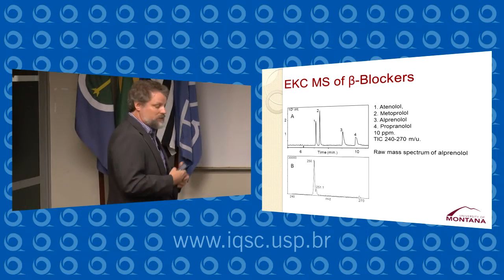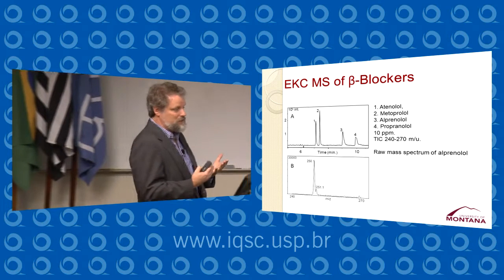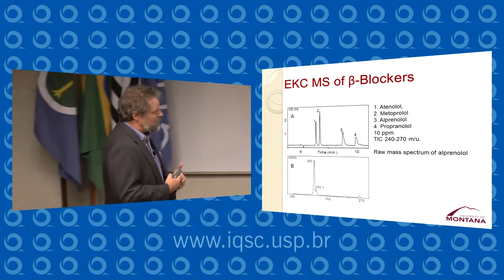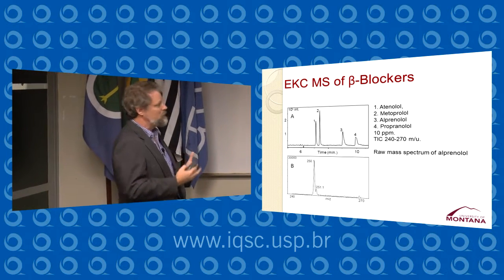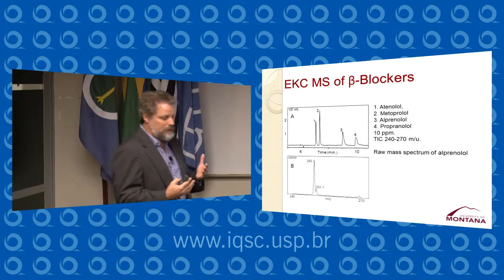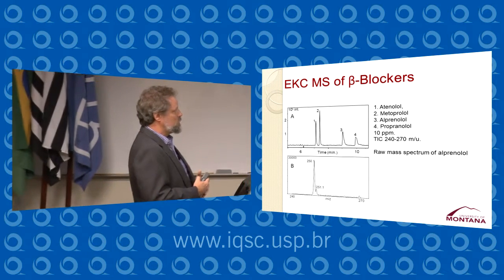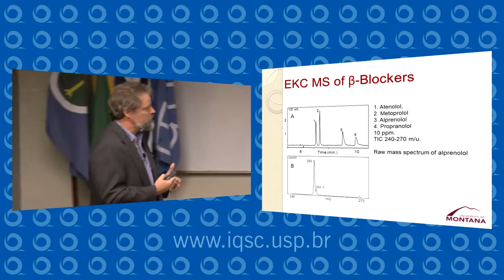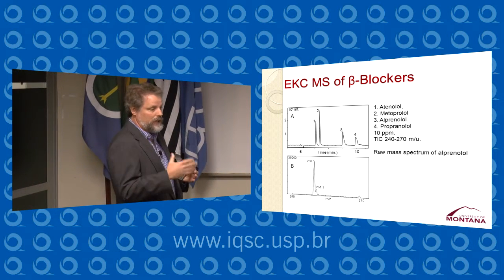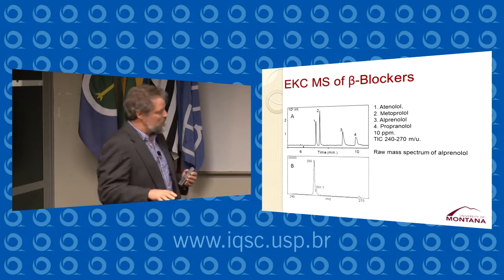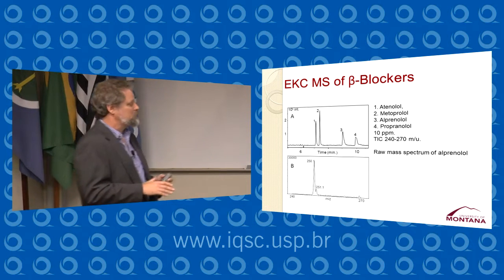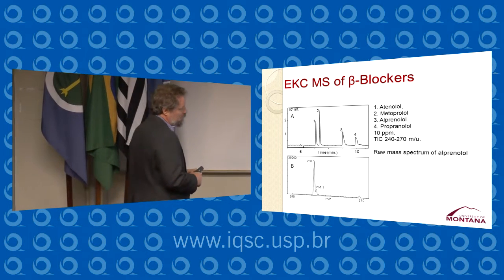So this works quite well, and in fact we ran these experiments for several weeks continuously without any problems clogging up the interface on the mass spectrometer. So the very low concentration of these nanoparticles combined with their very high molecular weight means that they don't interfere with the mass spec analysis in any way.